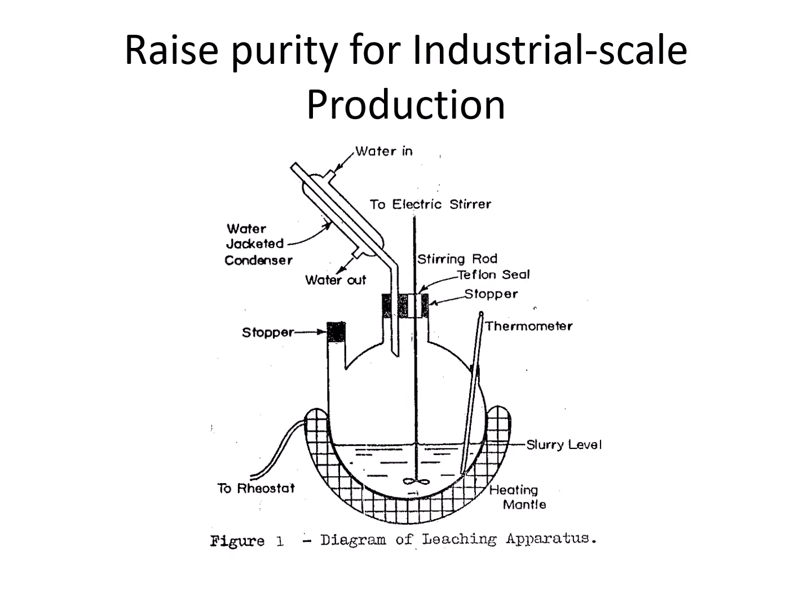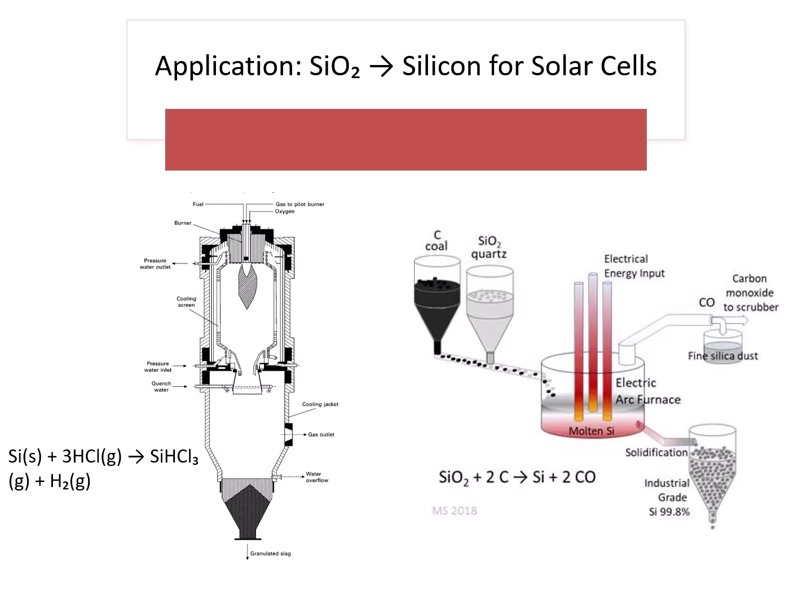For industrial scale silicon production, to raise the purity level, silica undergoes acid leaching using 5 to 10% hydrochloric acid to remove impurities like iron oxides, then thermal treatment at 800 to 1000 degrees Celsius for 2 to 6 hours to remove volatile impurities. The purified material is then crushed and sieved into fine grains of a finer silica powder. It is then converted into elemental silicon by a carbothermal reduction process, which is carried out in a submerged electric arc furnace operating between 1900 to 2000 degrees Celsius.